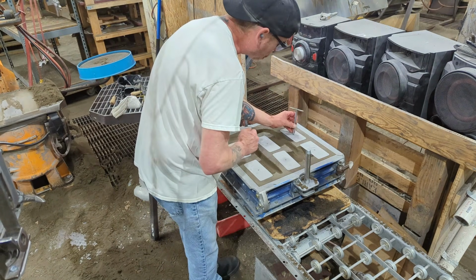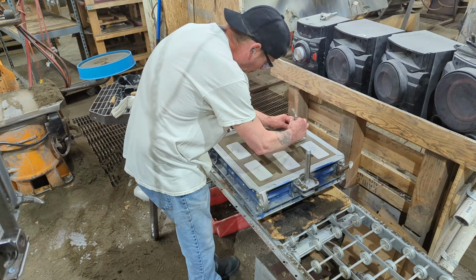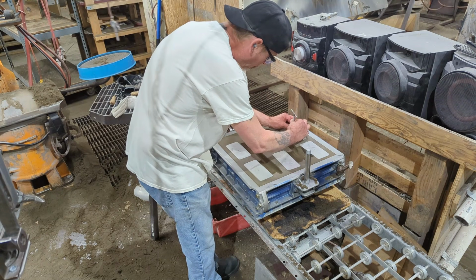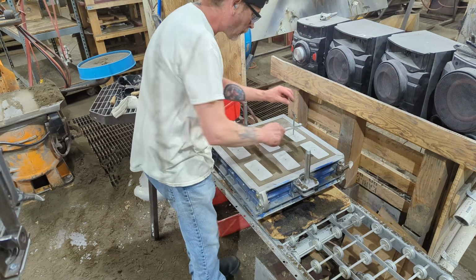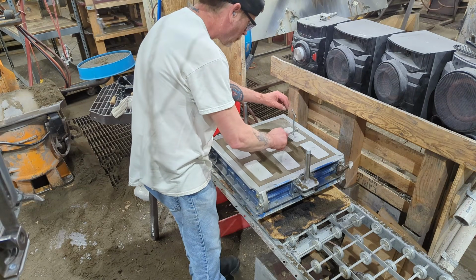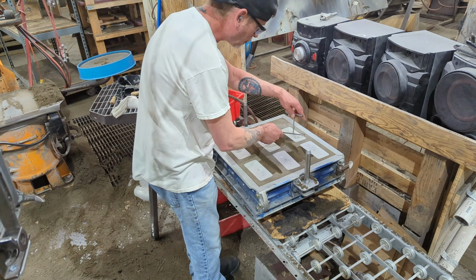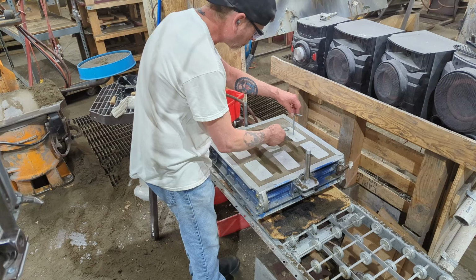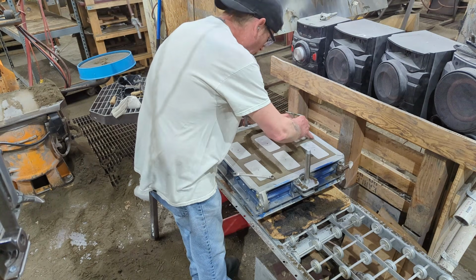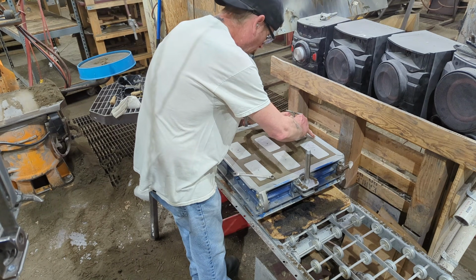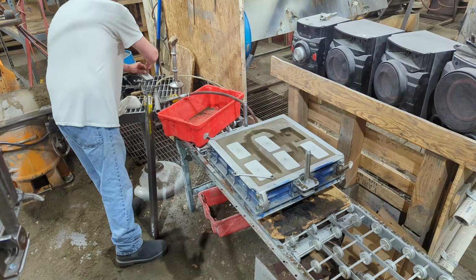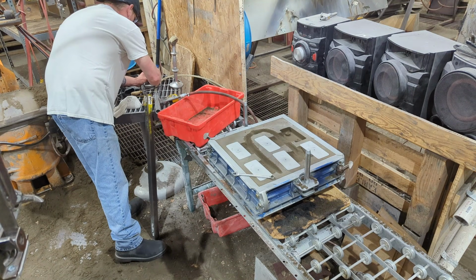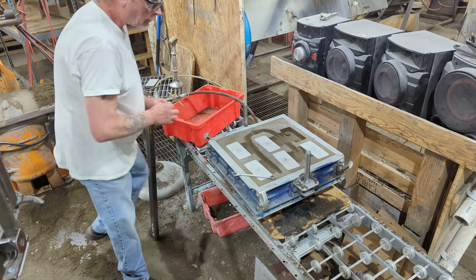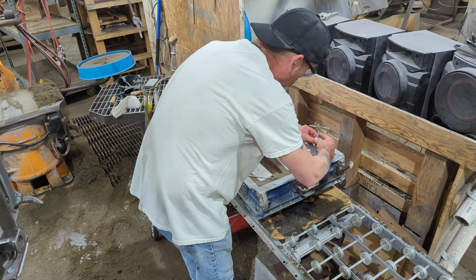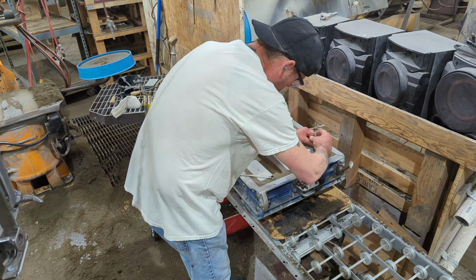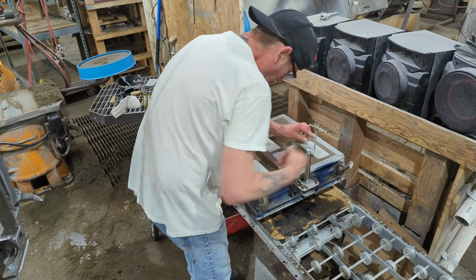Chad inserts a threaded lifting tool into each loose pattern and uses a small wrench to tap it free from the sand. He then gently draws each pattern straight up from the mold, leaving behind a clean cavity that will fill with molten zinc during the pour. He repeats this process for all 6 loose pieces.